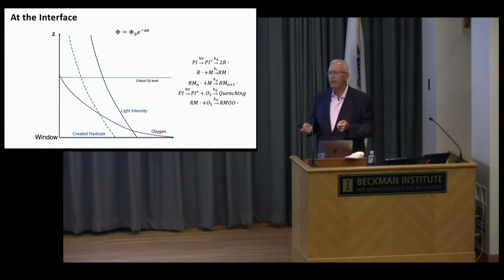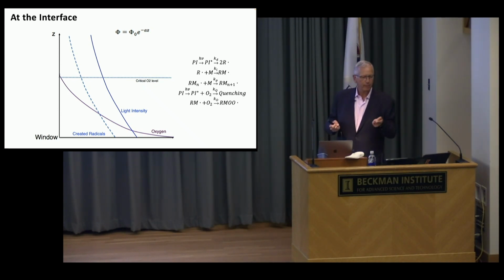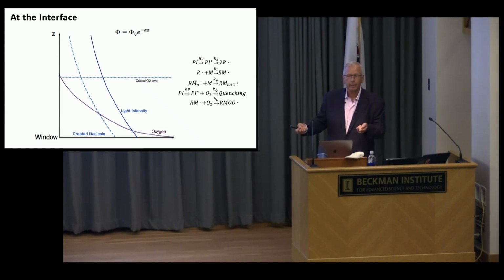And everybody that does free radical polymerizations knows that the first thing you typically do if you're doing a free radical polymerization in a round bottom flask is you degas your monomer. What are you doing? You're removing the oxygen. Because if you generate a radical in the presence of oxygen, the rate constant for reaction with oxygen is far greater than initiating a polymerization. That's why it's easy to ship monomers around. They're inhibited by oxygen and any added inhibitor. But if you degas your monomer, you don't want to ship that around because it can prematurely polymerize.